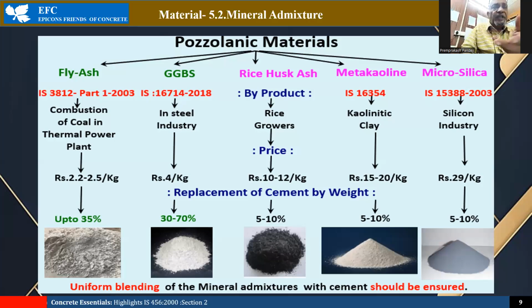These are pozzolanic materials which are mixed in the concrete, say fly ash, GGBS, rice husk, metakaolin, microsilica. These are added in various percentages and they change the physical property of concrete and its rate of gain of strength. The electrochemical environment of concrete is also changed because of this, and electrochemical environment is one factor which affects the rate of corrosion. So all these admixtures and chemical manipulations have an effect on corrosion.